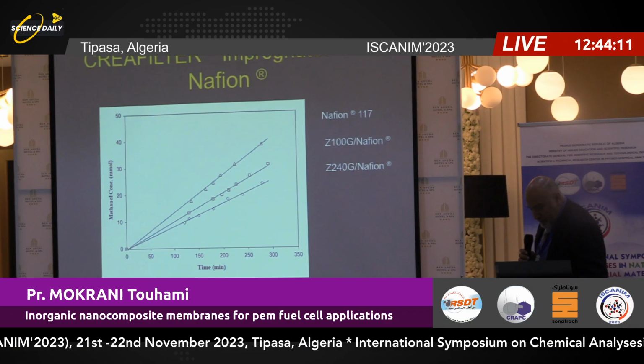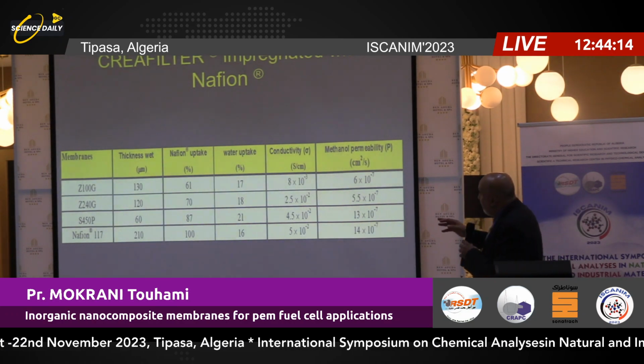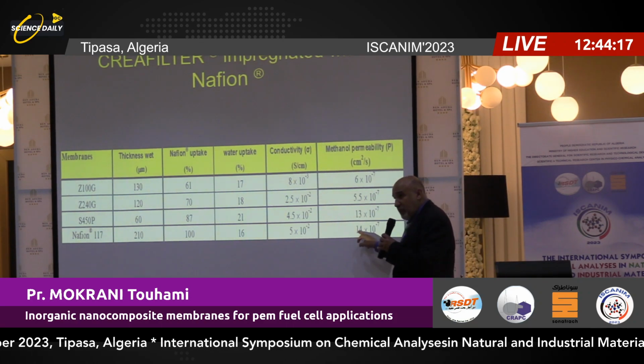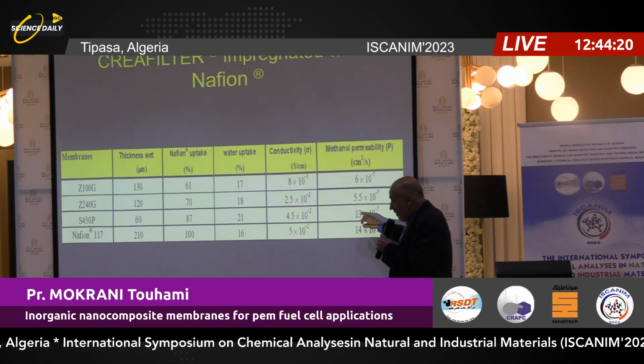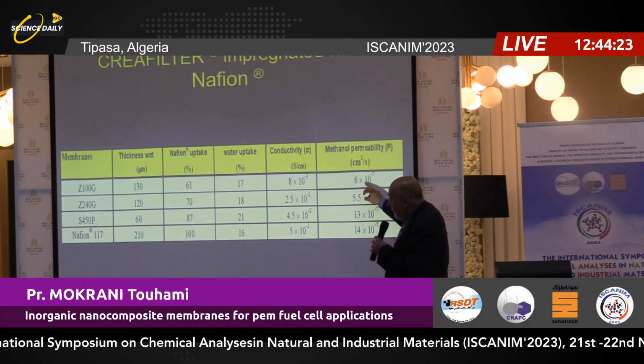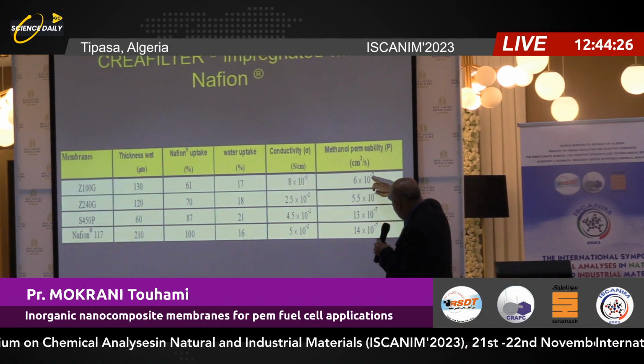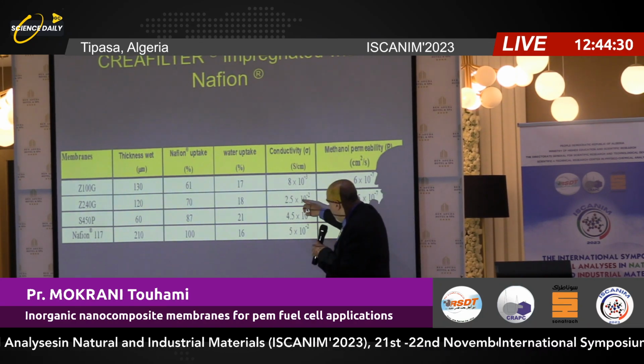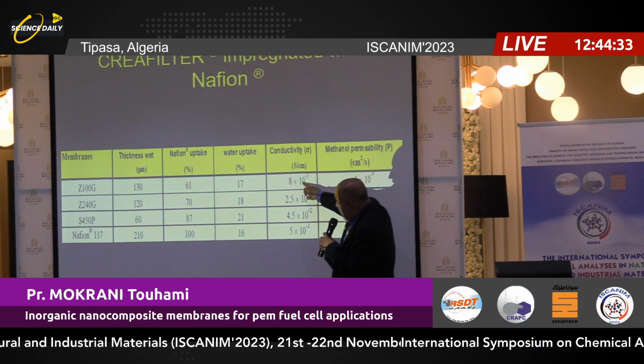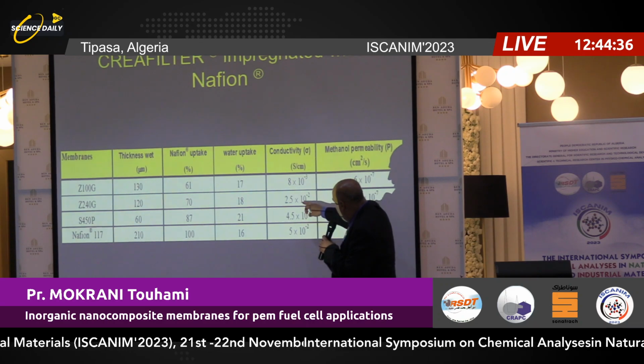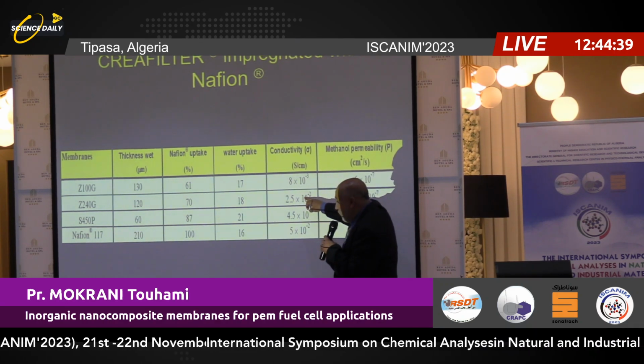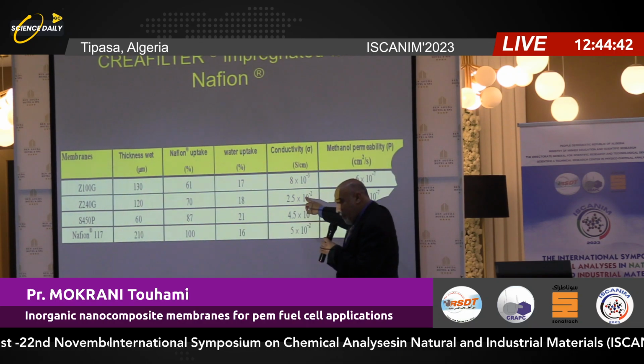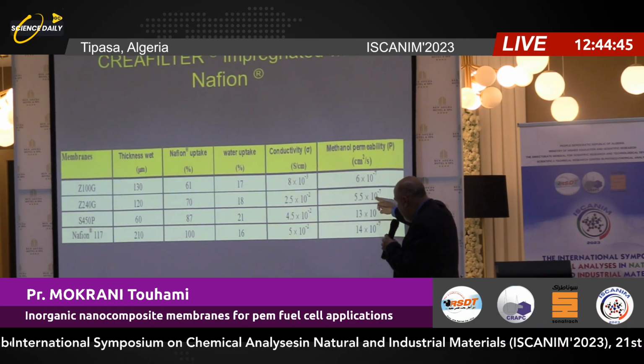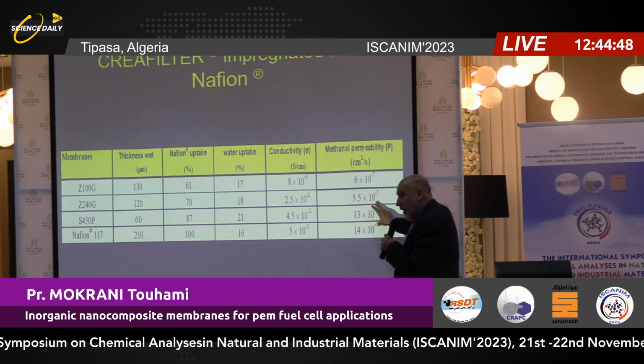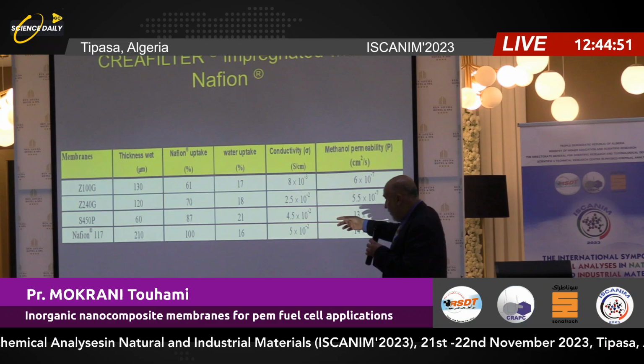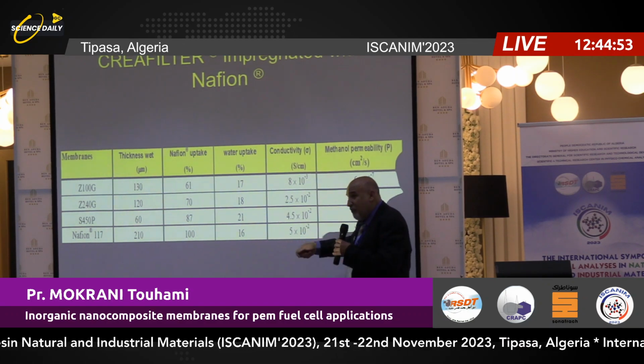And this membrane is very important because of the conductivity also. You can see here, okay, this one I don't like, but these two, I'm talking about the conductivity. So you can see here, okay, this one and this one. So this one, the conductivity is half, the permeability is better, and there is a third advantage of this material over this one, because this one is a film, Nafion film.